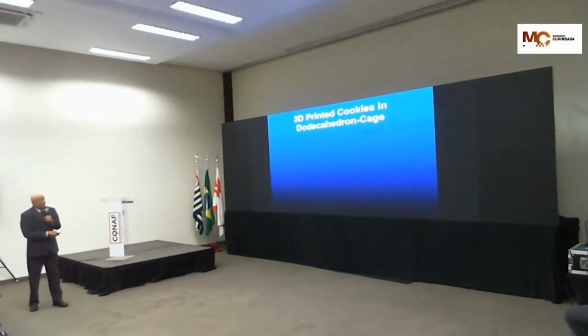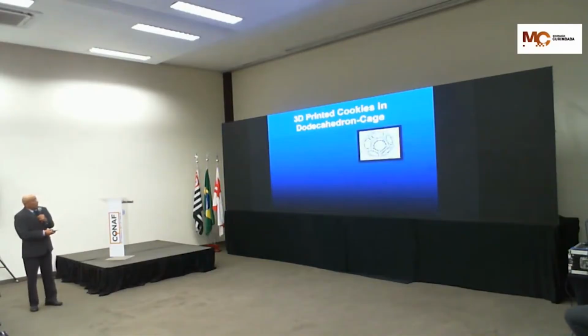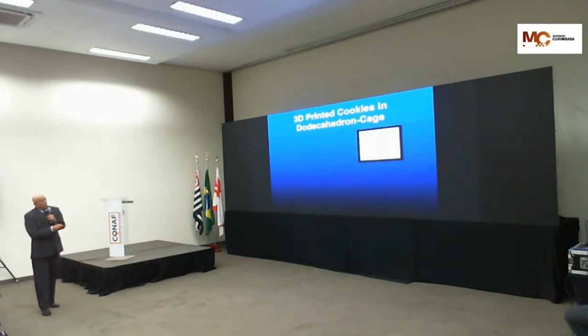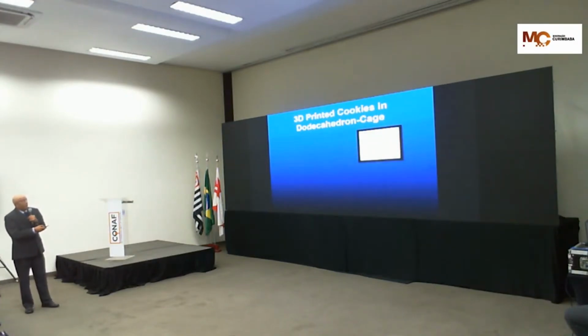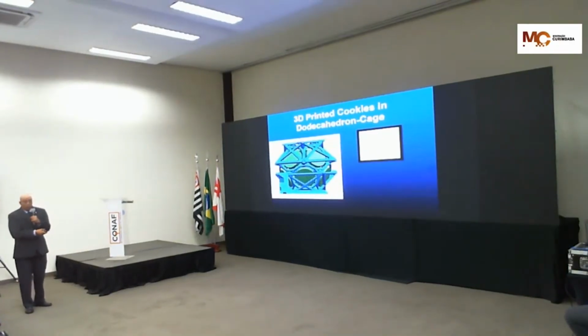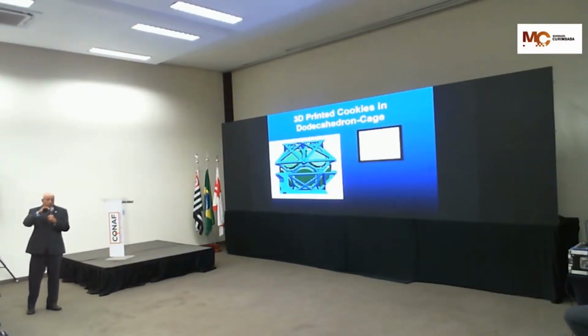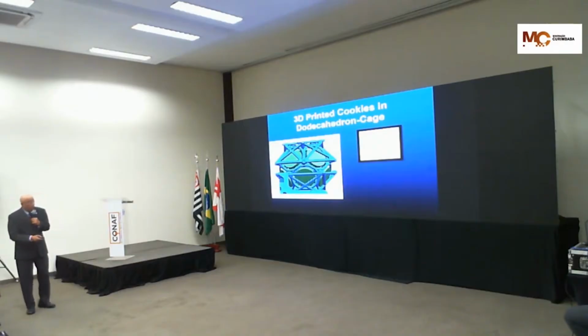With 3D printing technologies, I showed yesterday in a presentation, we have a model, and that model is a dodecahedron. It allows us to produce 13 specimens, 12 of them on the faces of the dodecahedron, and one that we randomly print in the center of the model. This is the cookie cage. The cookie cage allows us to ascribe the position in the build box, the height, the orientation, the print direction, so we can understand how these may cause variation in the metal casting process.